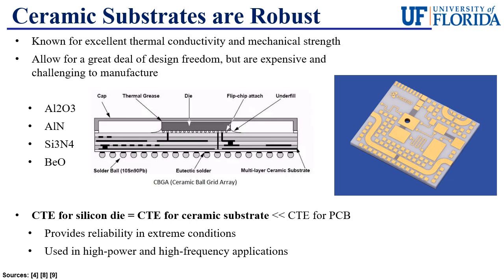Now, a more important quality for ceramic substrates is that they have a coefficient of thermal expansion that's well matched to silicon, meaning that thermal fluctuations are less likely to damage interconnections between the silicon die and ceramic substrate. And since the coefficient of thermal expansion is less than the PCB, when you design a ceramic substrate, you must keep in mind that the size of the package will affect the stress placed on the interconnections between the packaged substrate and the printed circuit board.